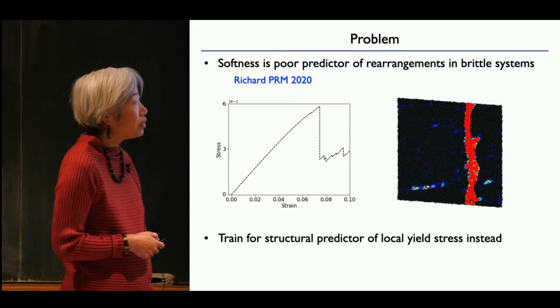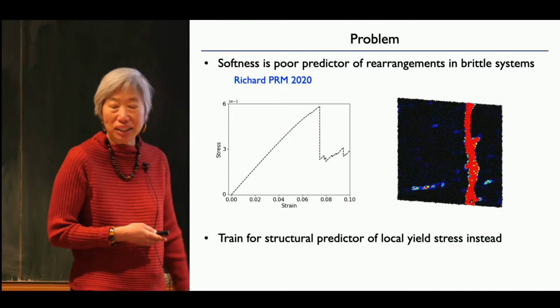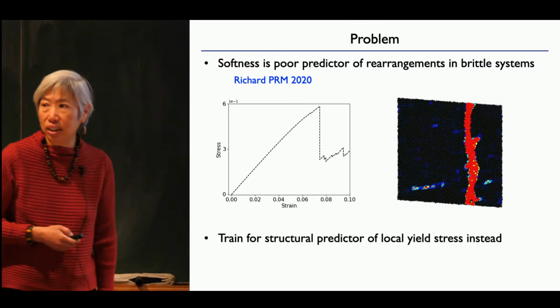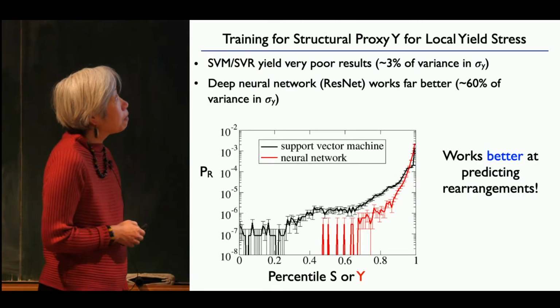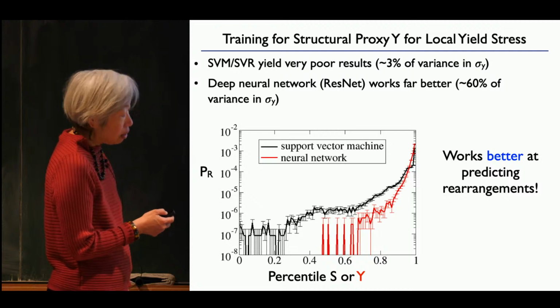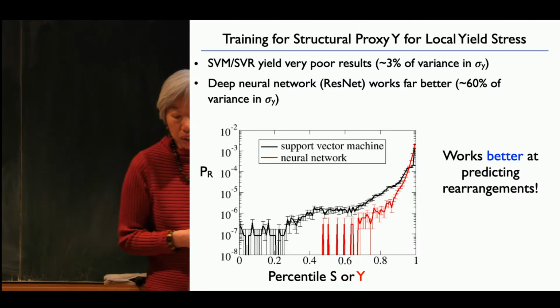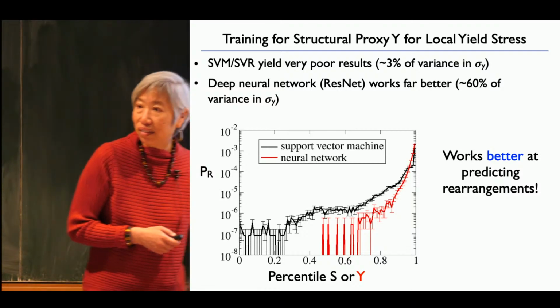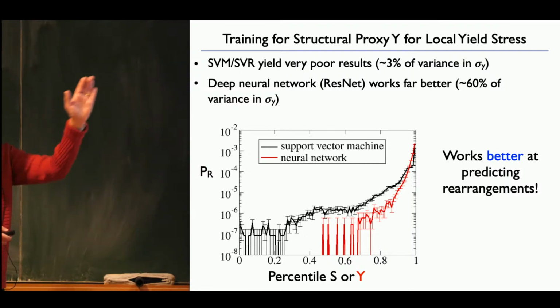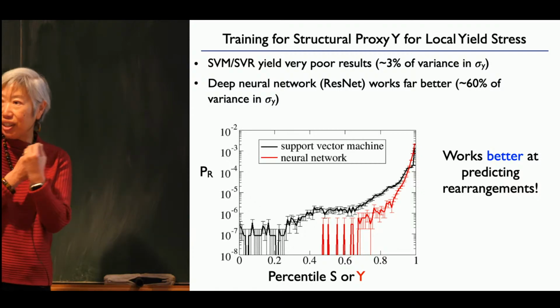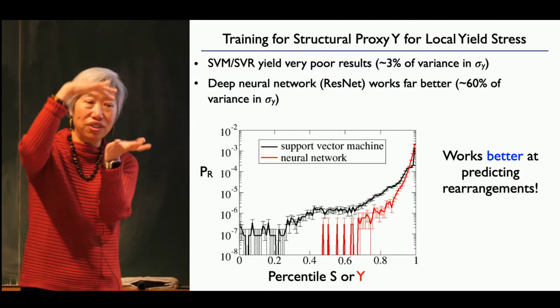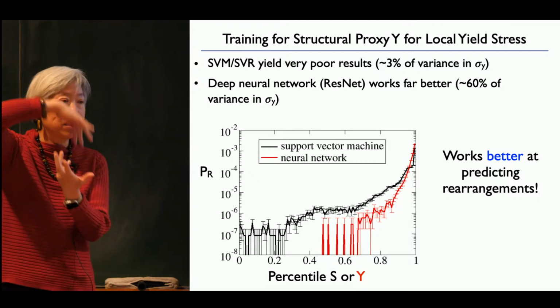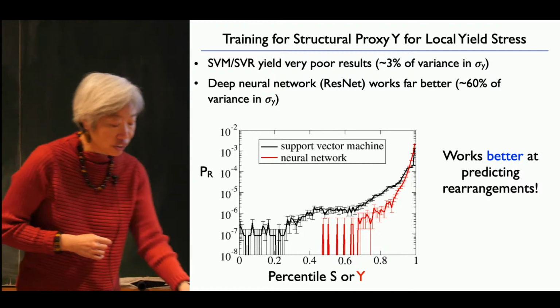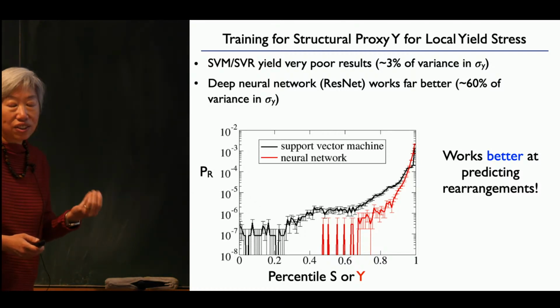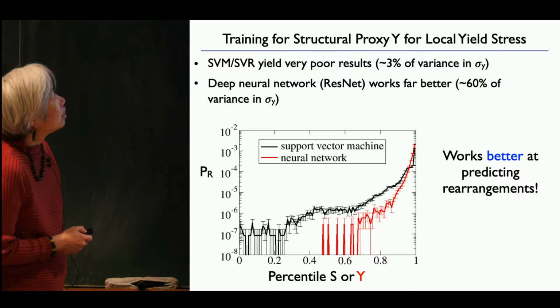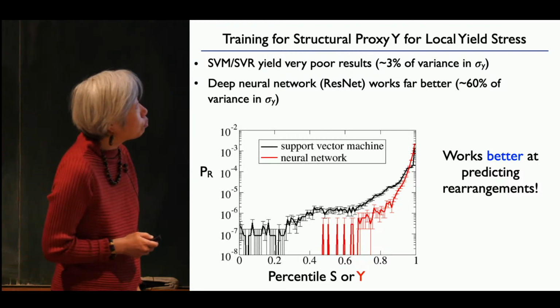And so what we wanted to do, instead of calculating the local yield stress, which is extremely expensive, was to train for a structural predictor of the yield stress instead. It turned out that the support vector machine is a very poor predictor, probably because it is a scalar, right? And the local yield stress has a direction associated. You shear in all directions. This is what David talked about yesterday. So the idea is you take a little region, you shear in all directions, and you ask, what is the direction in which the yield stress is the lowest? And that's the local yield stress. Because there's a direction associated, we think, the support vector machine or support vector regression work quite poorly.